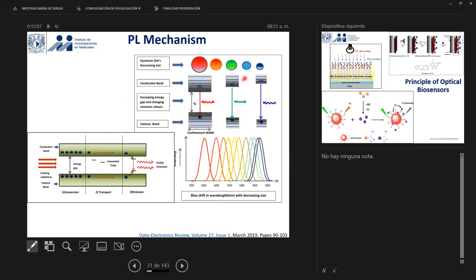What is that? So we have different sizes of nanomaterials, different sizes of nanoparticles. When the nanoparticles are smaller, we have a higher band gap. When they are bigger, larger in size, the band gap reduces. And when they are much larger, the band gap is much smaller. So you can see here, the concept is smaller size of nanoparticles, higher band gap, and we can have the emission in blue color. And when the size of nanoparticles is larger, small band gap, and the emission is in